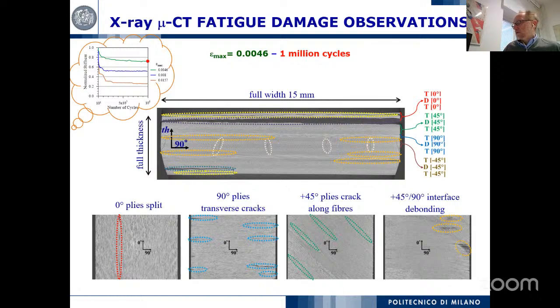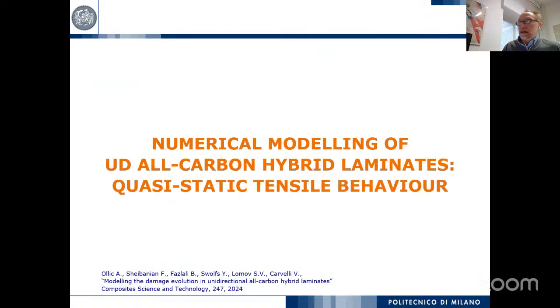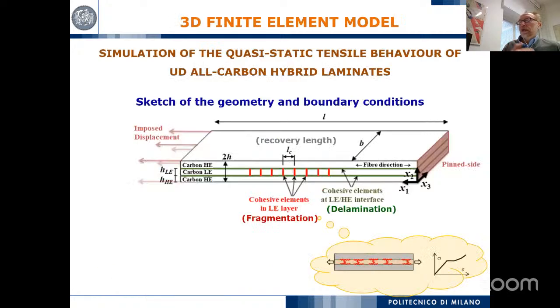Now, our question is, can we have a model that can help us to predict this behavior? And so we tried to develop a finite element model. In this case, it was limited to unidirectional laminates because they are probably the most interesting in terms of this pseudo-ductility, and it was limited to quasi-static loading too. What we want to reproduce in the model is the sequence of damage modes that we suppose, and that we have seen in the experimental tests.